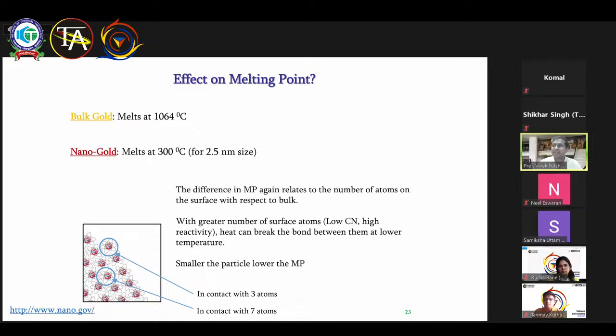Another example again is the melting point, right? The melting point of gold is 1064 degrees Celsius, really high. But if you make nano gold, gold of 2.5 nanometer size, then it will start melting at 300 degrees Celsius. Again, a significant change in the melting point. Now, why is that happening? If you look at the melting point in a very rough way, it is just moving the atoms away, some sort of increase in the bond distances between the atoms, so that they go into the liquid phase from the solid phase.